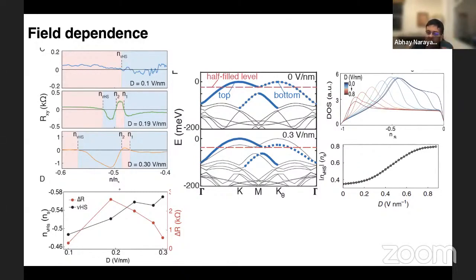So then the picture that arises is that the insulating state in this material is driven both by the fact that the density of states can be high when you tune the electric field properly, as well as correlations. And we have some support for this theoretical picture from the Hall effect. You can measure directly where this Van Hove point lies by the sign change of the Hall coefficient.